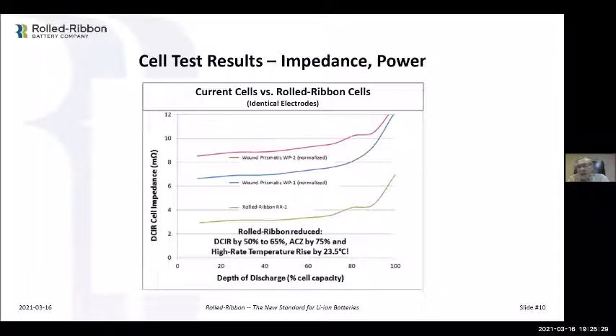With the thermal properties we have, we keep the cell cooler. It turns out the cells last longer when they stay cooler, even when you don't abuse them. They're going to last longer if you don't abuse them, and the cooler you keep them, the better they're going to behave. So what we found, for example, and I can tell you firsthand, we have an EChem partner. He uses an electrode to make cylindrical, pouch and prismatic cells. We get about 25 to 35% more cycle life, which makes the battery last longer at the same discharge rates he designed for his other cells. That's because we keep it cooler. Identical electrochemistry, right? We're using the same electrodes. There's nothing different about it. It's just cooler.